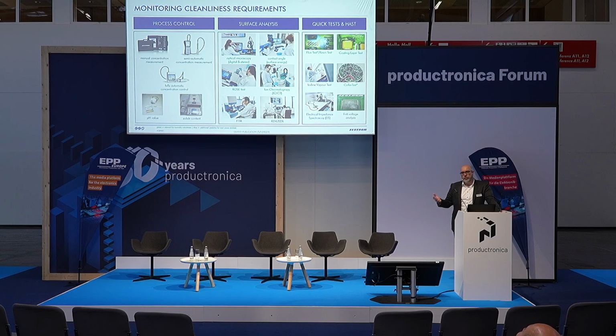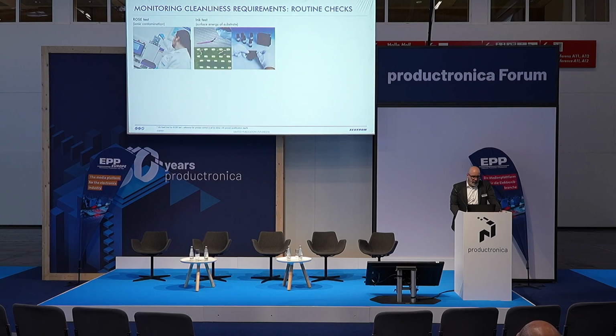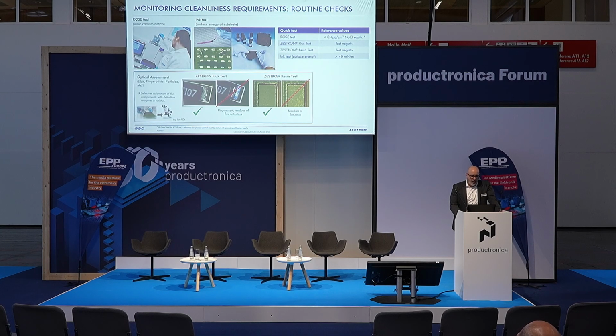And if you want to go deeper into that, there are also more reliable tests, like the coating reliability test. So you put the device underwater, under voltage, and you see if the coating is really protecting your device. And if you see any weaknesses in terms of bubbles or increased leakage current, this is an indication that maybe you need to improve your process. Okay, so in the last slide, I have some more details on these tests. But I think this is also in the handout. I don't know if you have this available later, but you can also check back with us.